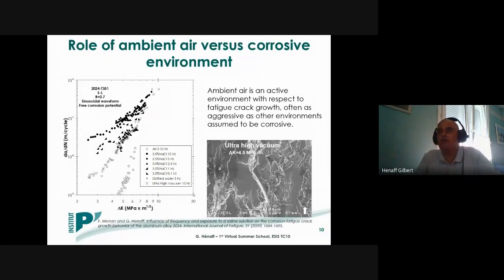So here, another illustration, in that case for fatigue crack propagation, in a case of 2024 aluminum alloy, where we compare the fatigue crack growth rates for different environmental conditions, namely ultra-high vacuum conditions here, which is in that case characterized by a special crack propagation mechanism that I will detail later on. And then some water environment, namely distilled water and a saline solution with different loading frequencies, and finally air.